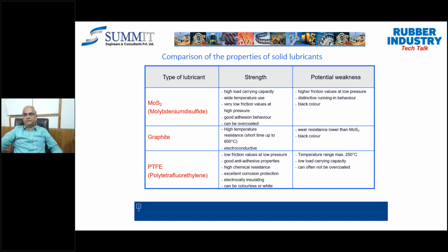The strength wise, if you really look into that, you will be able to find that more or less all the three have got a similar kind of behavior as far as the mechanical properties are concerned, like high load carrying capacity for the molybdenum disulfide, whereas the high temperature sustainability means I can sustain up to 500 to 600 degrees centigrade when I use the graphite.